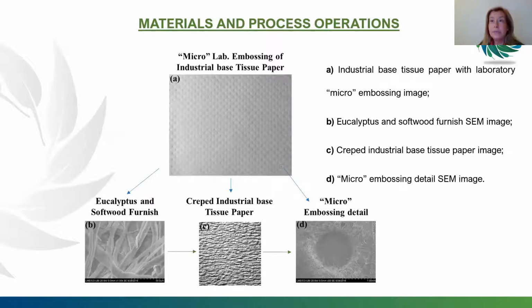In image A, we have an industrial-based creped paper embossed with the laboratory prototype, in which the micro-embossing pattern is visible. If we follow the green arrow here, we have in image B, at the fiber level, a blend of eucalyptus and softwood fibers, that is typical for tissue papers. In C, the topography of the creped paper, and in D, a detail of the concavity resulting from the embossing pattern, in the same image.